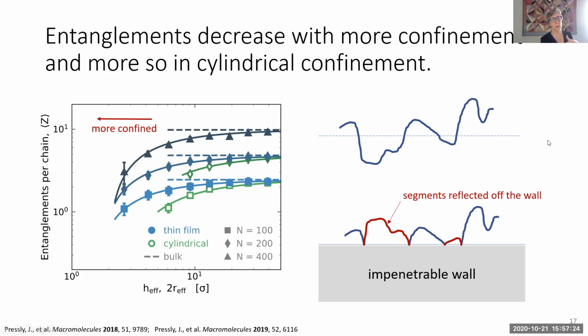And that's because when there's a random walk for a polymer and it's up against a wall, the chain reflects back on itself. So I just took that segment of the polymer and flipped it back off the wall. So the chain segments are reflected off the wall. And if this polymer is occupying more volume near the wall, that means other polymers are displaced. So with entanglements, you can only count an entanglement when it's two different polymers. So that's how we understand this drop off in the entanglements per chain as the system becomes more confined.